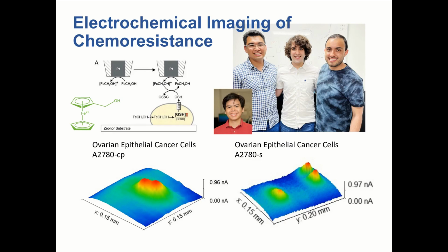And then when the electrode scans over our cells, it is basically regenerating the ferrocene methanol by the oxidation of the glutathione. That is shown here in the top left scheme. And as a result, we get these beautiful diffusion maps of cells and the surrounding glutathione. In the figure below, you see in blue our Petri dish, and you see green and these colors basically show how the glutathione is diffusing from cells and creates a sphere around them. So that is a very good visualization of the events that we are tracking here.